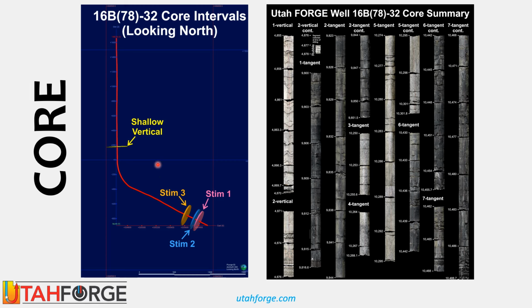Here I'm showing the trajectory of 16B, and these thin discs represent depths over which core was taken. The core is shown here over the right-hand side. So we grabbed a core here in the shallow vertical section. That's this nice white one over here. And then we jumped down to near the toe, where we cored through zones which we had previously stimulated, looking for the fractures that we made.